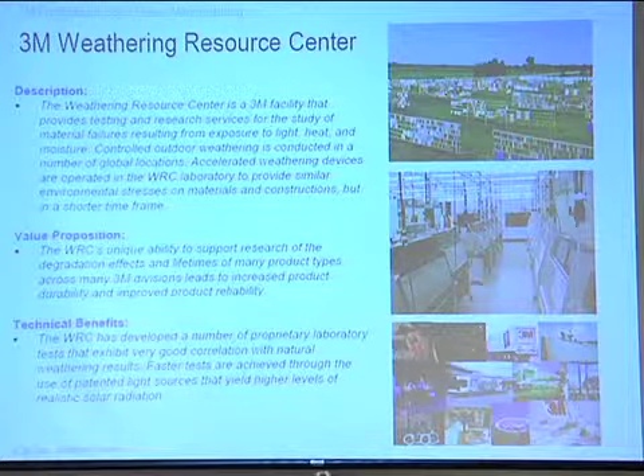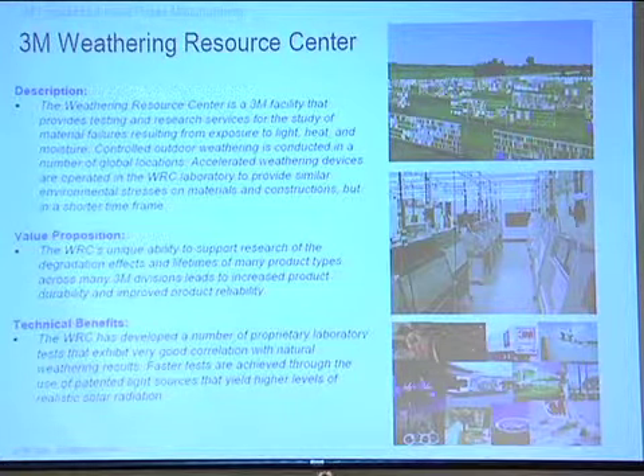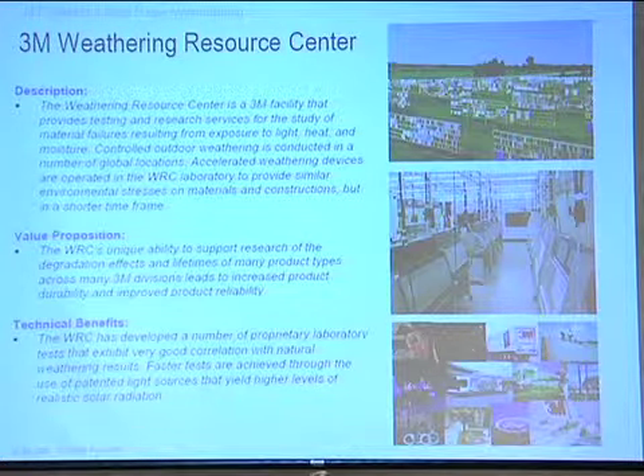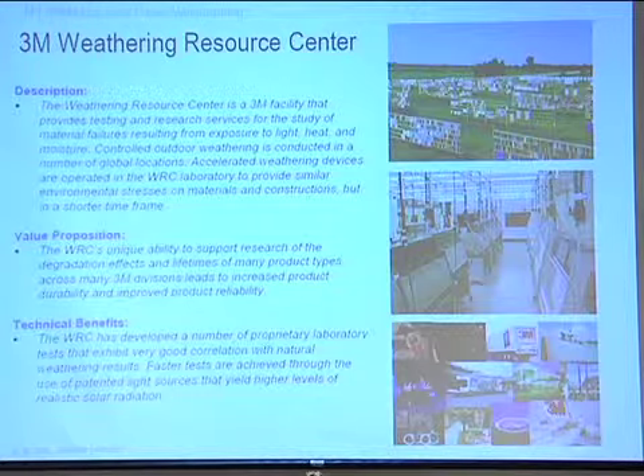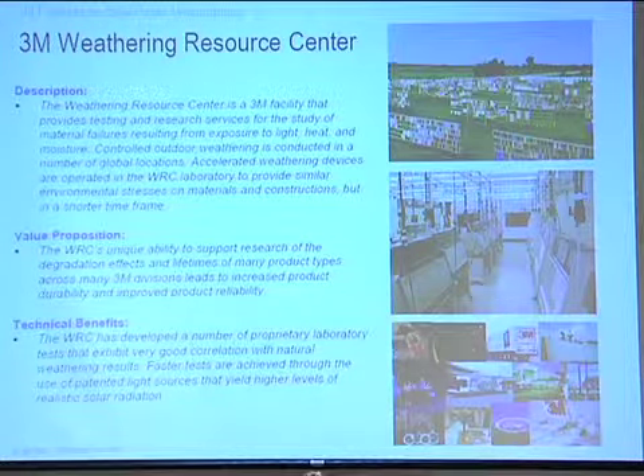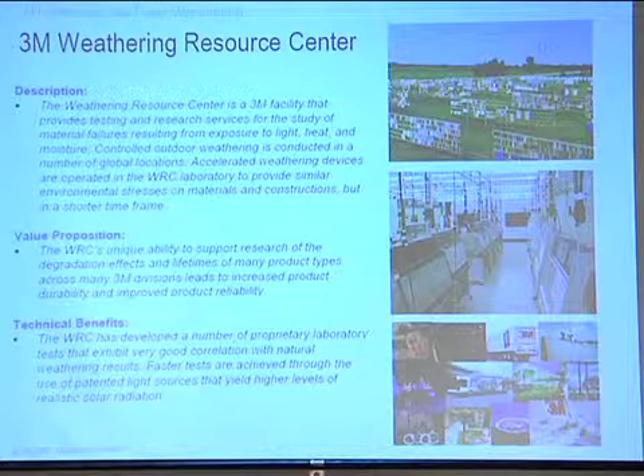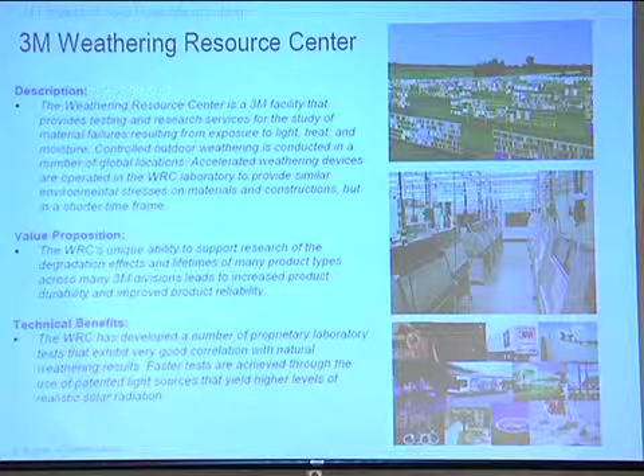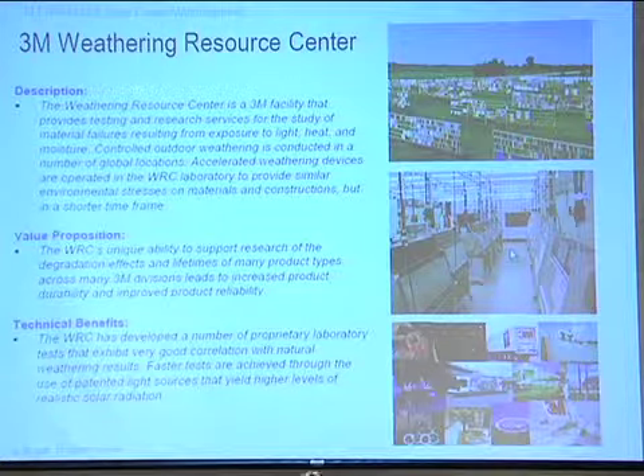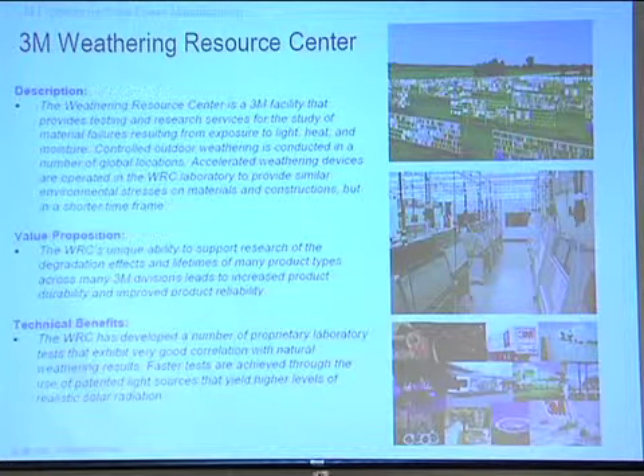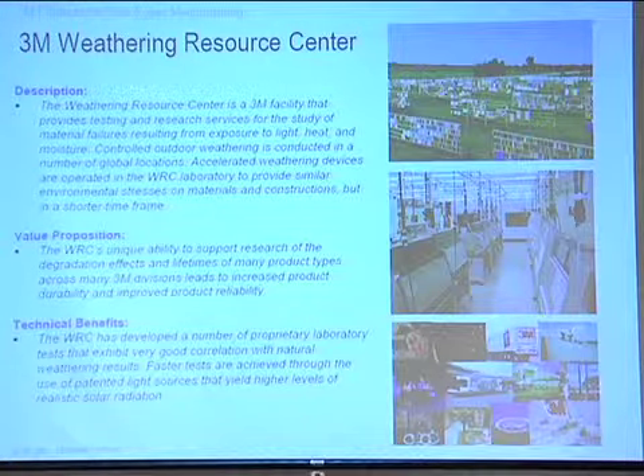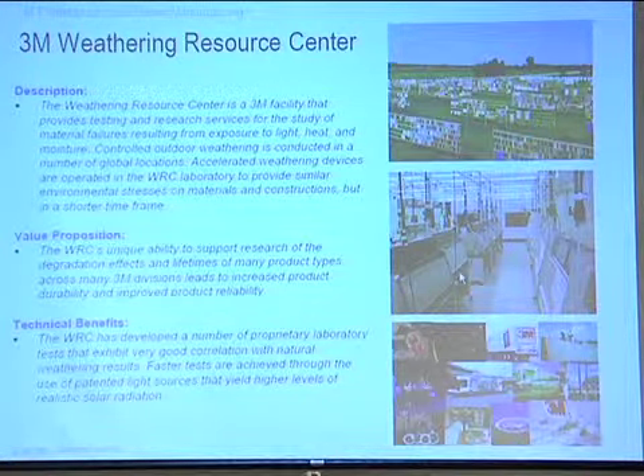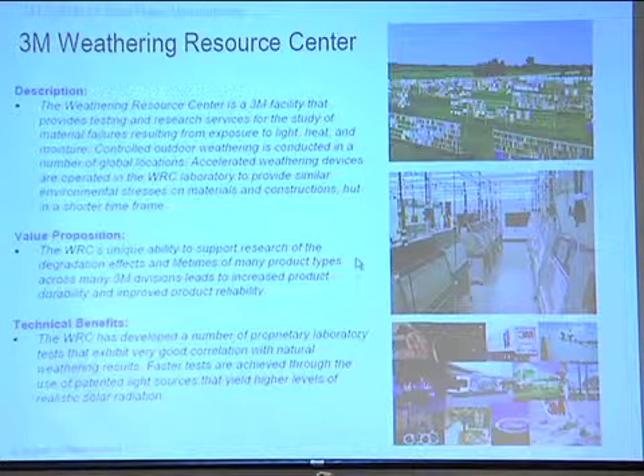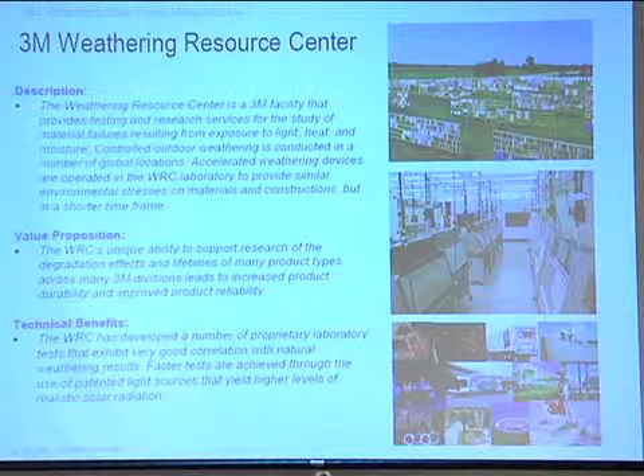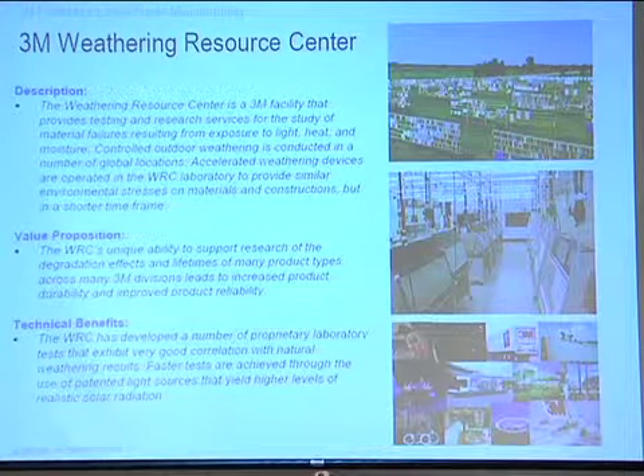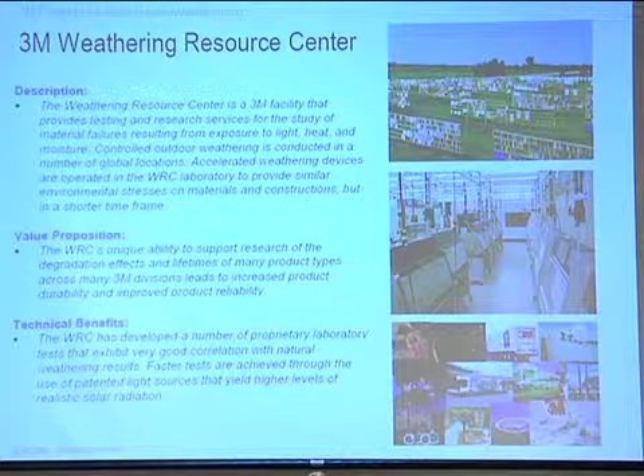One of 3M's advantages is we have a very extensive weathering resource center where we do predictive modeling of how long a polymer or any material will last outdoors. This is down at Cottage Grove where, I'm sure you know, most of the traffic signs in Minnesota are made with 3M materials, so we test all these materials outside. And then indoors we have these accelerated weathering chambers where we expose materials to more light, 10 times the light they would see outside, and heat and humidity. And by cycling materials through all these conditions, you can create models that allow you to predict how long they'll last outside. And this is a huge advantage for 3M developing polymeric films, tapes, and adhesives that are intended to last outside a long time.